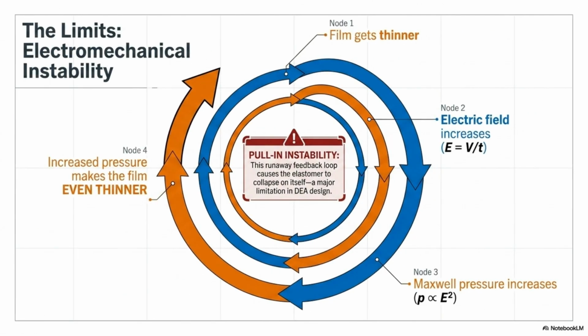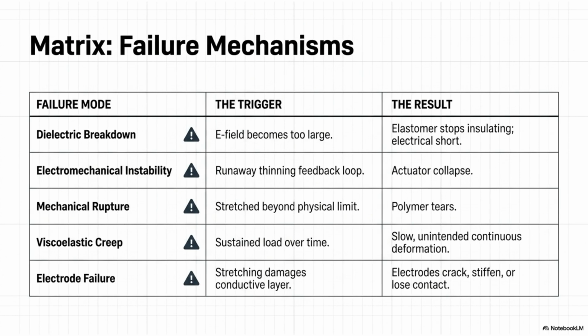A major limitation is electromechanical instability, or pull-in instability. This is a runaway feedback loop where the film getting thinner increases the electric field and Maxwell pressure, which makes the film even thinner, causing collapse. Failure mechanisms include dielectric breakdown from an excessive E field, electromechanical instability causing collapse, mechanical rupture from overstretching, viscoelastic creep from sustained load, and electrode failure due to stretching damage.